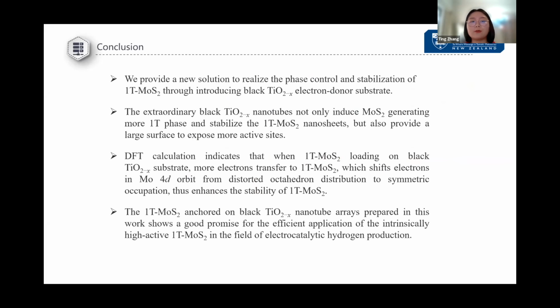Then we come to the conclusion that we have provided a new solution to realize the phase control and stabilization of the 1T-MoS2 through introducing the black titanium dioxide electron donator substrate. And the extraordinary black titanium dioxide nanotube not only induced MoS2 to generate more 1T phase, but also stabilized the 1T phase during the reaction and exposed more active sites. The DFT calculation also indicates that the electrons of the Mo 4d orbit are enhanced, and thus enhanced the stability of 1T-MoS2.